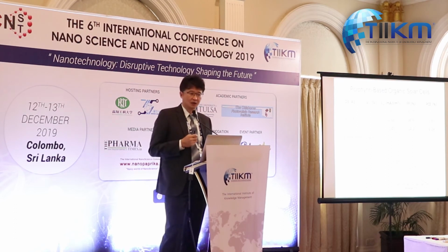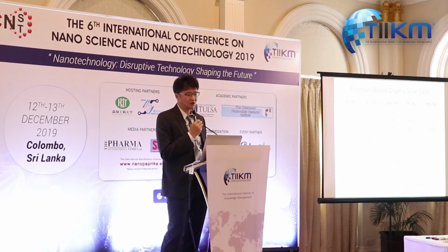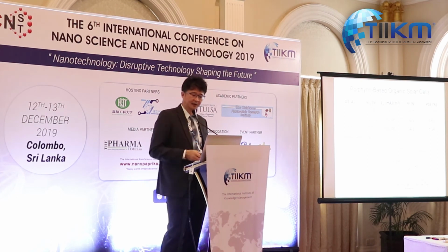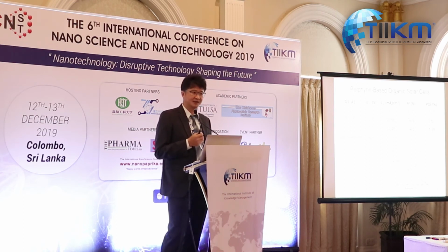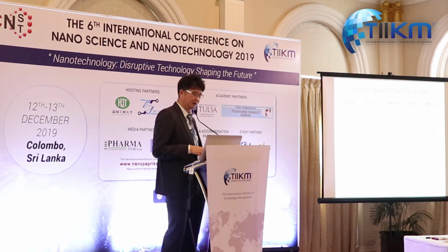And we recently developed a new donor and acceptor for small molecule organic solar cell. The device shows broad IPCE spectra covering the visible and near IR region, with fair IPCE values, and a decrease of the amount of the acceptor results in an increase in the PCE. The optimized ratio of D1 and A1 gives a PCE of 7.21% for the best performing device.